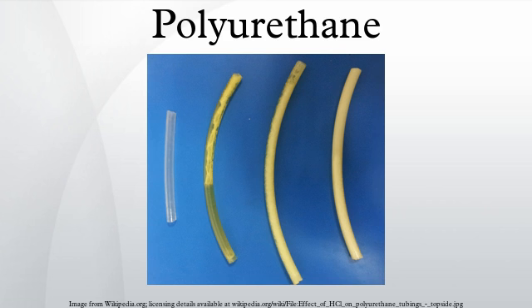Two-component fluorinated polyurethanes prepared by reacting FEVE fluorinated polyols with polyisocyanate have been applied to make ambient cure paint coatings. Since fluorinated polyurethanes contain a high percentage of the fluorine-carbon bond, which is the strongest bond among all chemical bonds, fluorinated polyurethanes have excellent resistance to UV, acids, alkali, salts, chemicals, solvents, weathering, corrosion, fungi and microbial attack. These have become the first choice for high-performance coating paints.